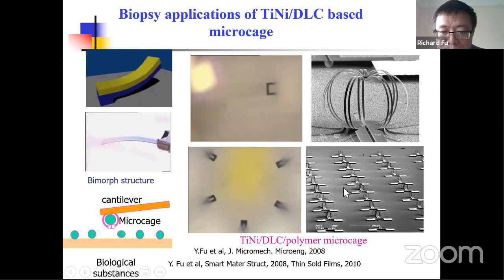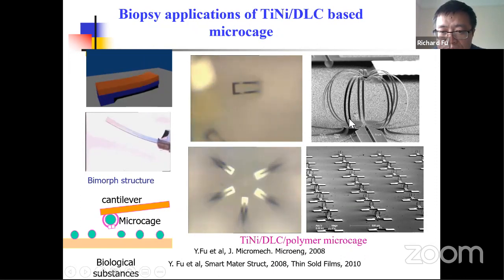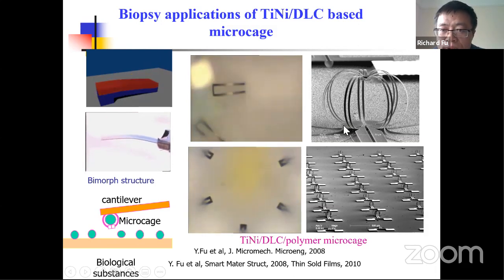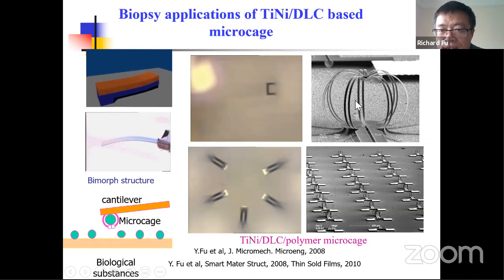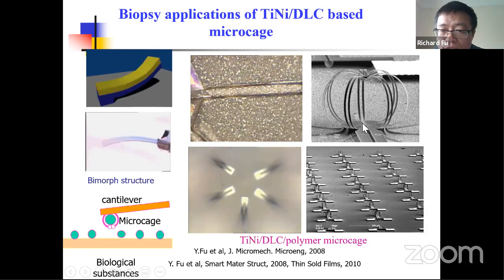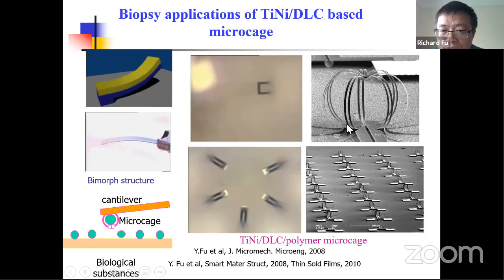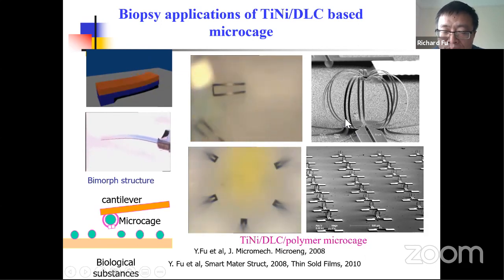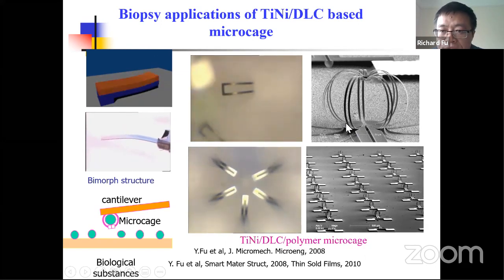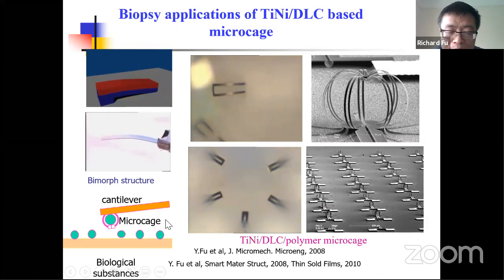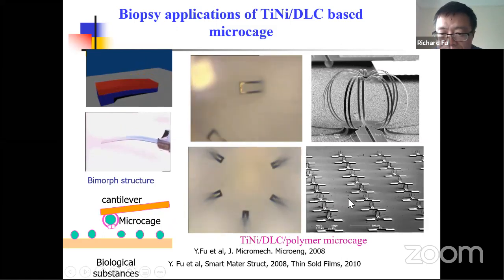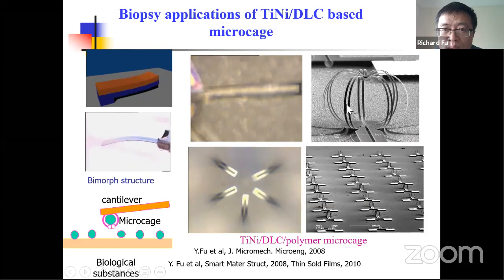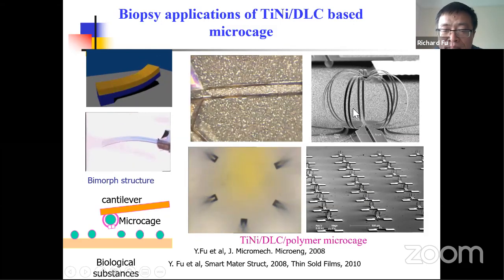The reason we use diamond-like carbon is because it has very large stress. Once we release the substrate from the silicon, the large stress will bend the cantilever structure significantly, so it forms the cage shape. If we let current flow through these fingers, it causes a shape memory effect. It becomes flat, so it will open up significantly to pick up things. So we can design different structures and form the two-layer titanium nickel and diamond-like carbon.